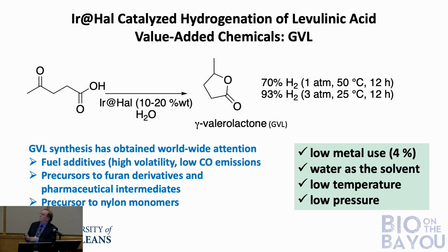Now we are in the process of developing the levulinic acid chemistry. Here we've done hydrogenation of levulinic acid using our catalyst. We need a little bit more material, a little bit more iridium. We can get this conversion at 70%, 1 atmosphere and 50 degrees. But if we increase the pressure to 3 atmospheres, which is certainly something we can do in an educational or in an academic laboratory, this is very doable, and we can reduce the temperature down to 25 degrees. Okay, so basically, with our iridium halloysite, we have improved the catalytic activity and access to these compounds, which industrially right now is way out of this range in terms of ease of operation.